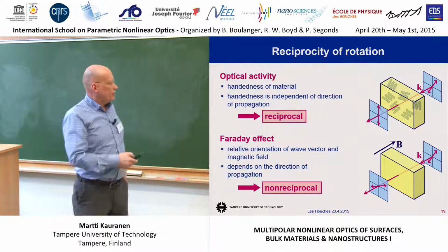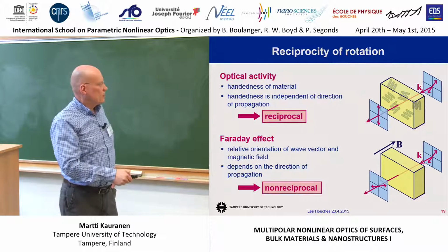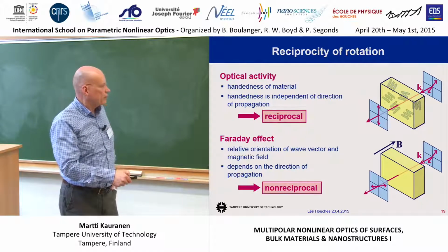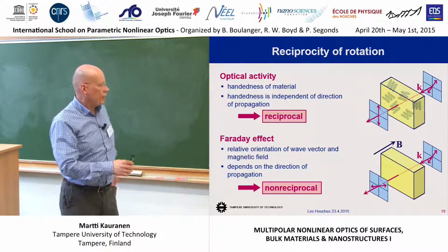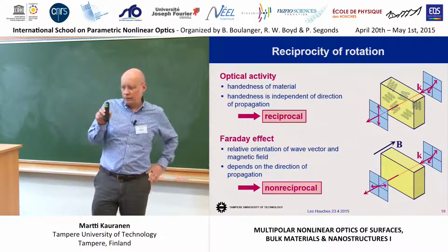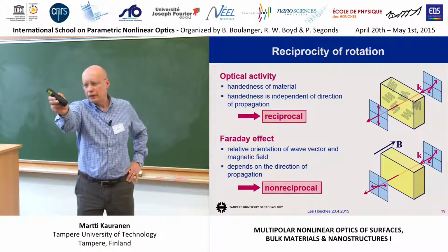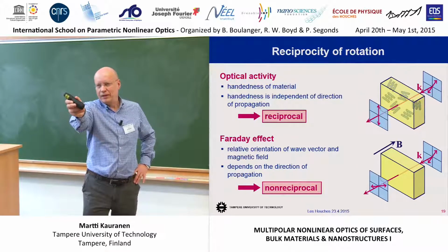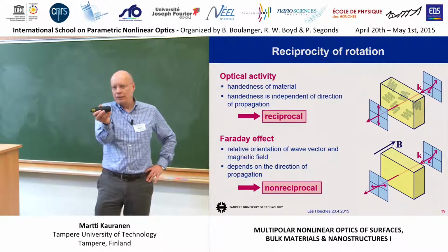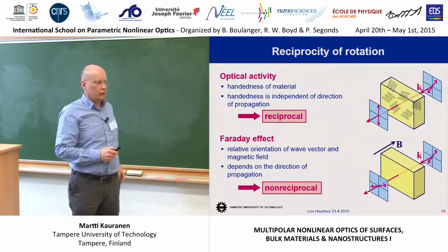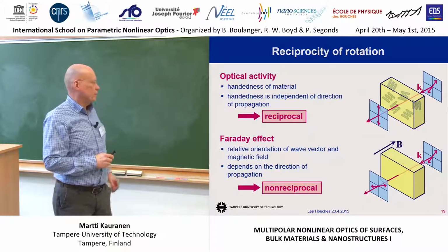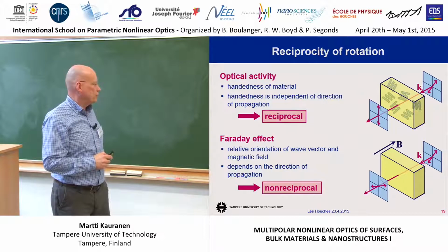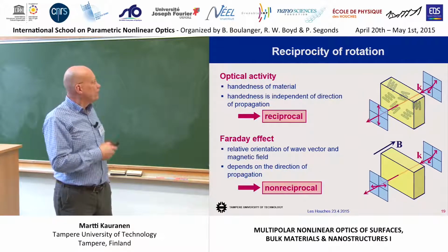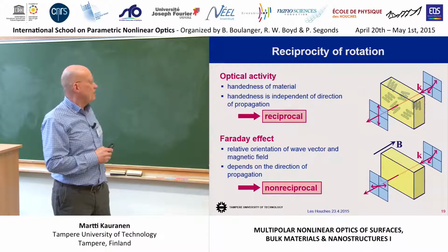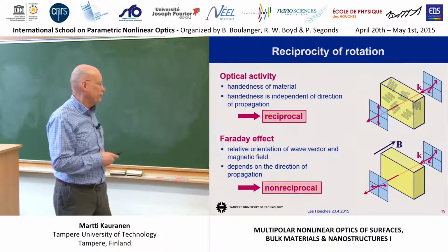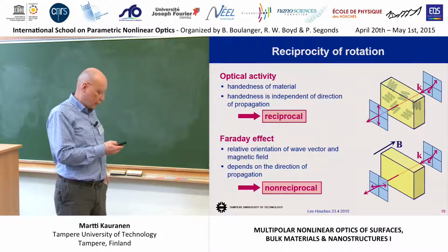In the Faraday effect, when you're coming back, the relative orientation of the k vector and the B field has been changed, and therefore if you go in, you rotate this way, you come back, you rotate in the other direction, I mean relative sense, so you can end up here, which is the basis for Faraday isolators. You can isolate, let's say, your experiment from your laser. So optical activity is a reciprocal effect. Faraday rotation is a non-reciprocal effect because of the presence of the magnetic interaction.